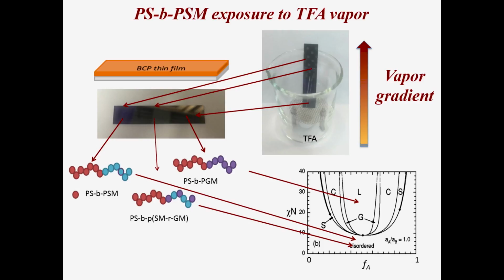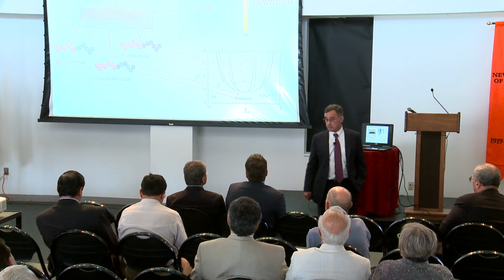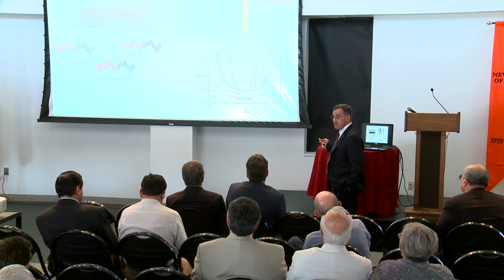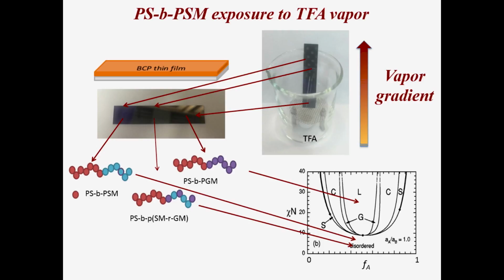All right, and so what that means is that at the base here, I'm closer to the trifluoroacetic acid, so the vapor pressure is much higher. The concentration of TFA is much higher. So at the bottom, I've converted the material to polyglycerol methacrylate. The top, I haven't done anything to it. So I've basically taken a film, and if I look at the bottom, it's over here. I've converted the poly(solketal methacrylate) to polyglycerol methacrylate, and in the middle, I have some sort of random copolymer.